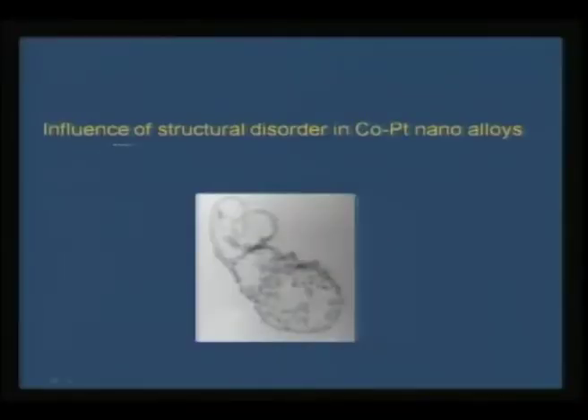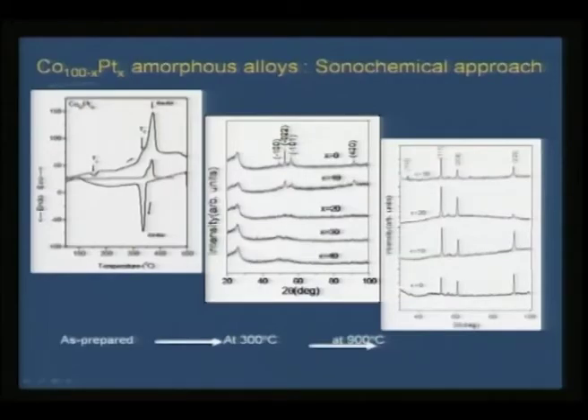Now what is so great about these cobalt platinum nanoalloys? Cobalt platinum nanoalloys show structural disorder, and this can influence the magnetic property or catalytic property to a greater extent. If you take the cobalt platinum amorphous alloys that we have prepared using the sonochemical approach, you can see the phase transformation that is occurring. If you do the DSC curve for cobalt platinum, the first peak you see here is the glass transition temperature, and this amorphous alloy is getting crystallized somewhere around 350 degrees C. So if you want to study this in amorphous form, you should always restrict the temperature for treating these particles well below 300.